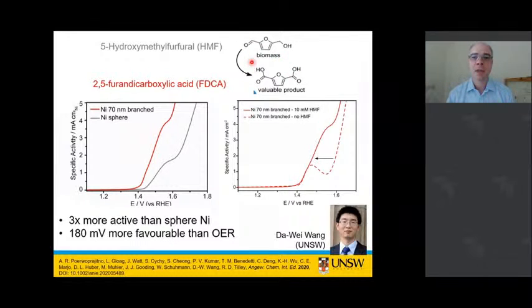So when you're doing your biomass oxidation, you're taking your HMF and oxidizing it up and turning it into a more valuable product at the end of the catalytic reaction, so turning it into your FDCA. And as I said, the catalyst with the longer branched arms were the most effective catalysts, and they were 3 times more active than spherical nickel nanoparticles. If we compare how good a catalyst they are for a harder reaction like OER, then they weren't great catalysts, but for oxidizing biomass they are actually pretty efficient catalysts. Some of this catalysis study was done in collaboration with Da Wei, who's another colleague from UNSW.